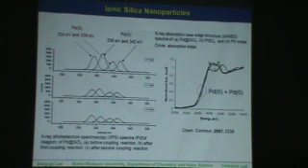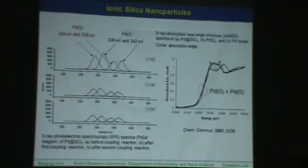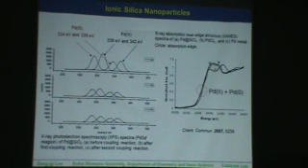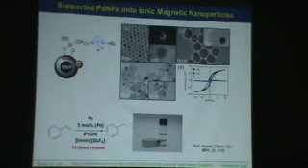And then we found out from this analysis that in the first reaction, palladium 2 and 0 are mixed, and then after recycling of this material, it's slowly gathering to form the palladium 0 species to get the palladium nanoparticles. We got this information from the XPS experiment. But this is the final slide probably. We have also modified the magnetic nanoparticles and then added the palladium nanoparticle to utilize this magnetically separable catalytic system. So we used this 10 times.